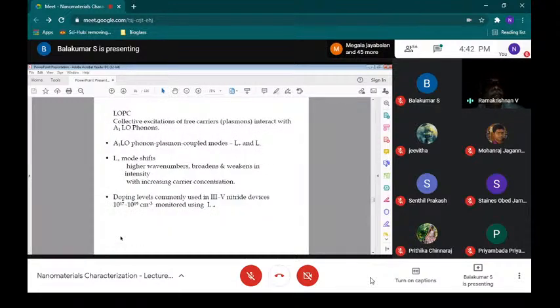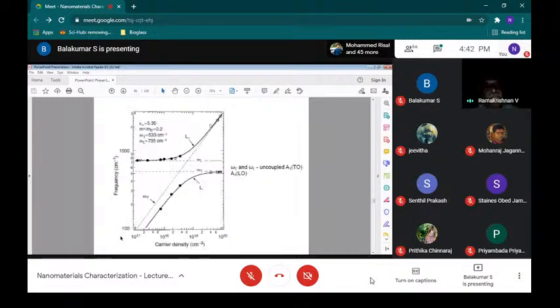The LOPC mode, longitudinal optical phonon coupling mode. That is what I said, the collective excitations of free carriers interact with the phonons. Now you can say this L plus is the positive coupled mode. L minus is the negative coupled mode. Omega T and omega L are the uncoupled A1 TO mode and A1 LO mode. These LO or TO modes can couple with the plasma modes. Then you have the L plus mode and L minus mode. From the L plus and L minus mode frequencies, you can evaluate the carrier concentration.